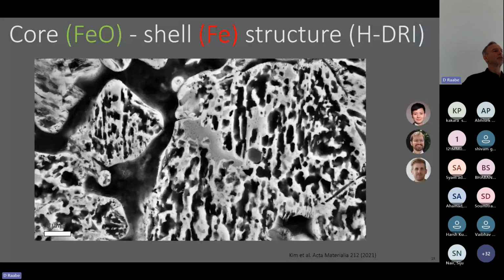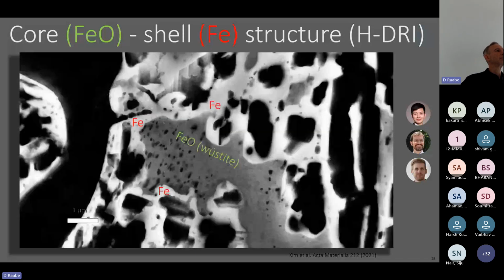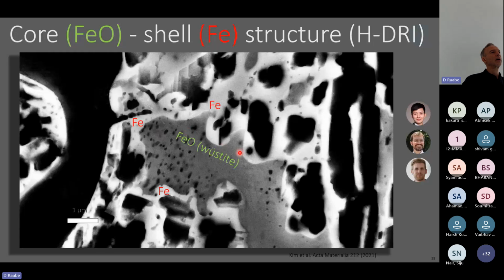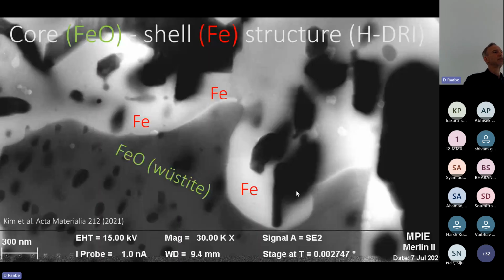That means the take-home message from this very slide is that you produce very quickly, of course, core-shell structures. And the oxygen must be transported outbound through these relatively dense iron layers. As you can see here, when I highlight that a little bit better at higher magnification, now in a cross section, then you can see that here are areas with patches where you have remaining iron oxide wüstite at 700 degrees centigrade, again on purpose at a relatively low temperature. But then you can see that the iron layer forms rather densely around that wüstite. And you need to bring out that oxygen, and that must then diffuse through that relatively dense iron layer. So that makes things relatively sluggish to proceed.